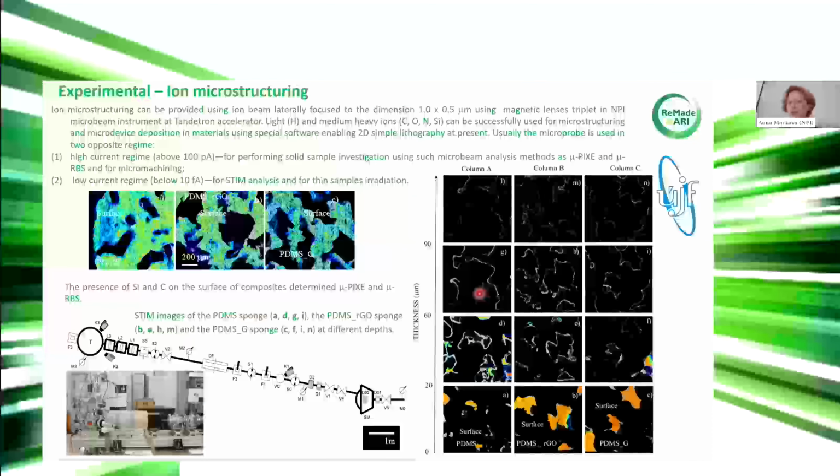So from this, we can, let's say, qualitatively get the depth profiles. But we have to be careful, of course, because we are doing depth profiles for very porous materials. Anyway, it's information on how much gold and silver we introduced and what the distribution is. Here we see the prediction, which is pretty narrow. In effect, finally, this implant is much more spread over the zinc oxide nanorods.